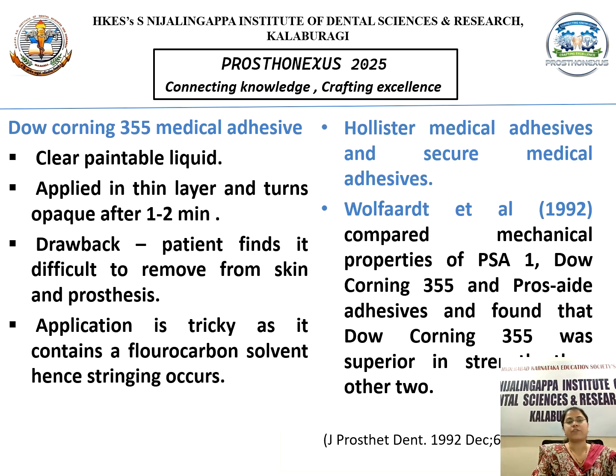The Dow Corning 355 medical adhesive is a clear paintable liquid, applied in a thin layer, and turns opaque after 1 to 2 minutes. But the drawback of this material is that the patient finds it difficult to remove from the skin and prosthesis. The application is tricky as it contains a fluorocarbon solvent, hence a stringing occurs. Hollister Medical Adhesives and Secure Medical Adhesives. Wolfaardt et al. in 1992 compared the mechanical properties of PSA1, Dow Corning 355 and Pros-aide adhesives and found that the Dow Corning 355 was superior in strength to the other two.